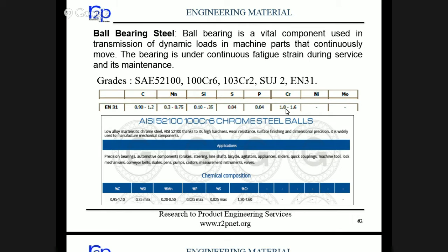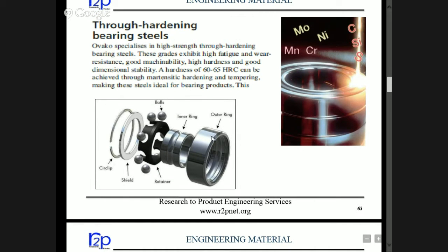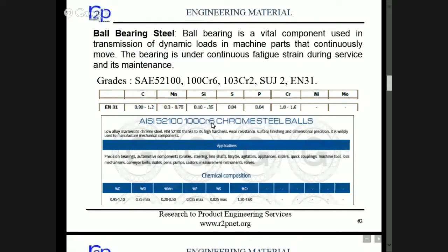But the only precaution to be taken in case of through hardening steel components is that after hardening, tempering is a must in this case. Otherwise, it can even break if you drop it from this side. It becomes so brittle. So without tempering, no through hardening steel can work. So these are the components shown here of a bearing: the outer ring, inner ring, balls, retainer. They are all made of through hardening steels. 100Cr6, which I showed you. Yeah, 100Cr6. This is a very common material for through hardened steel bearings.